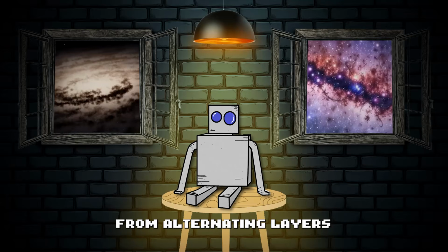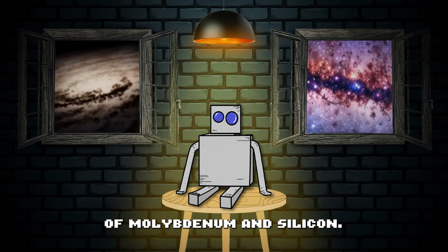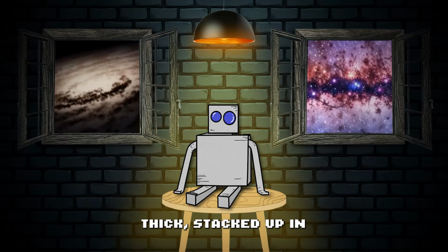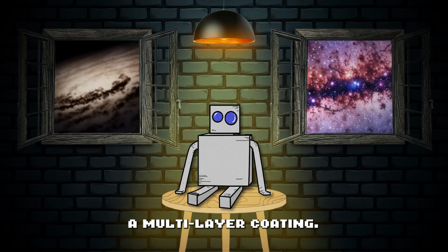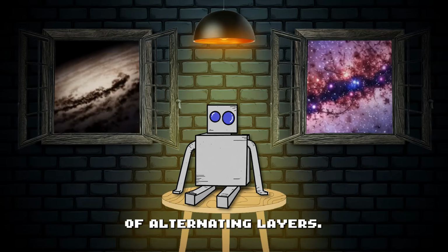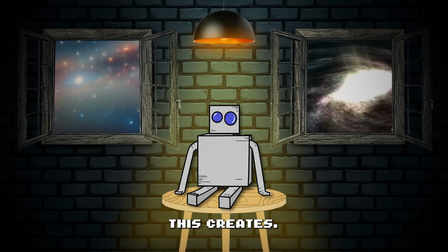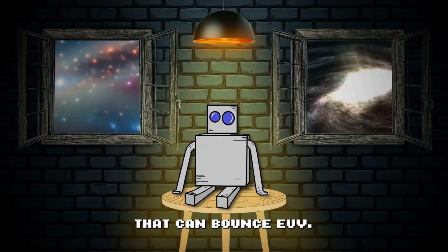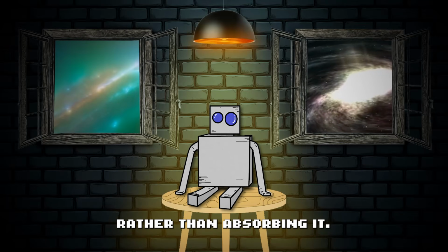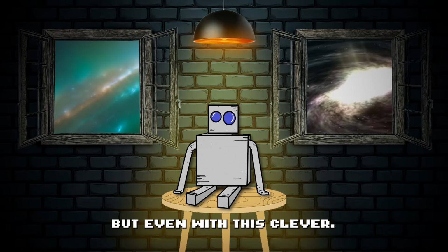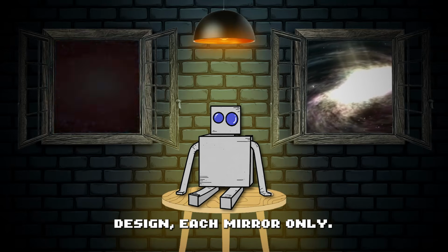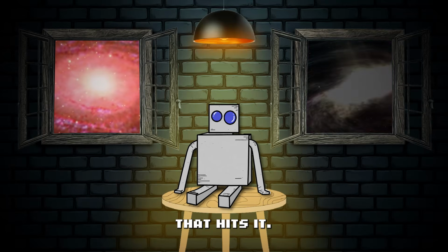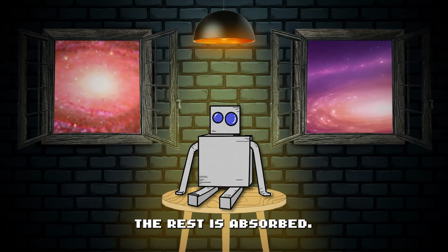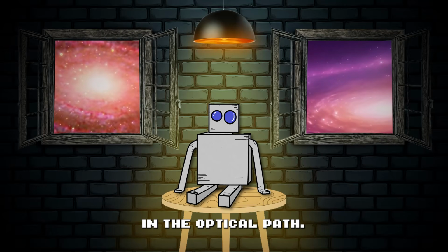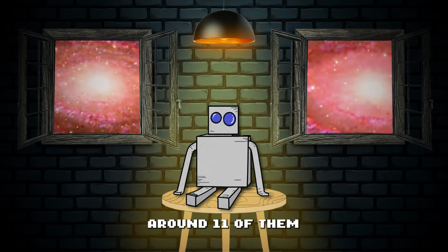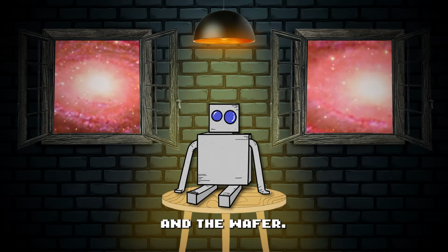They're made from alternating layers of molybdenum and silicon, each layer just a few nanometers thick, stacked up in what's called a multi-layer coating, about 40 pairs of alternating layers. This creates a kind of Bragg reflector that can bounce EUV light rather than absorbing it. But even with this clever design, each mirror only reflects about 70% of the light that hits it. The rest is absorbed. And there are multiple mirrors in the optical path, typically around 11 of them between the light source and the wafer.